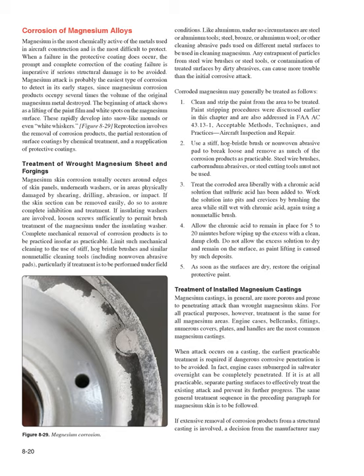Treatment of wrought magnesium sheet and forgings. Magnesium skin corrosion usually occurs around edges of skin panels, underneath washers, or in areas physically damaged by shearing, drilling, abrasion, or impact. If the skin section can be removed easily, do so to assure complete inhibition and treatment. If insulating washers are involved, loosen screws sufficiently to permit brush treatment of the magnesium under the insulating washer. Complete mechanical removal of corrosion products is to be practiced insofar as practicable.